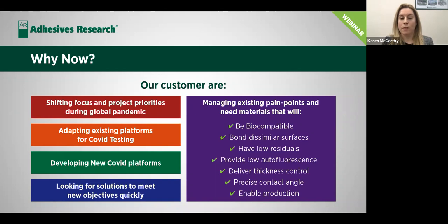So this allows the dissimilar surfaces to be combined together. Also looking for low residuals. If you've high residuals within the adhesive or the construction, they can outgas over time and interfere with the reagent chemistry. So it's critical to keep these low. Low autofluorescence can be desirable depending on your method of detection within your device. Obviously, if your method of detection is fluorescence, you don't want any background fluorescence coming from the adhesive construction.